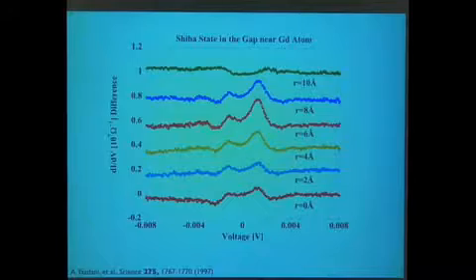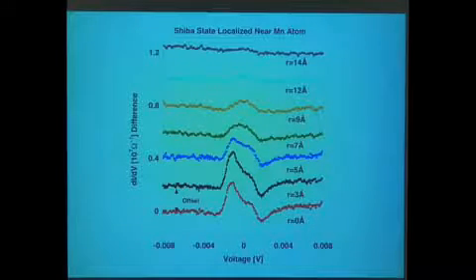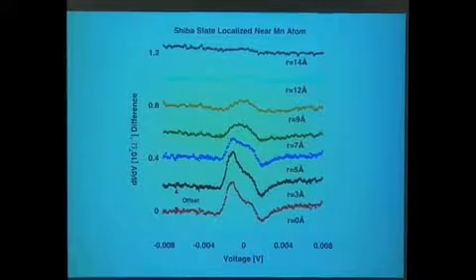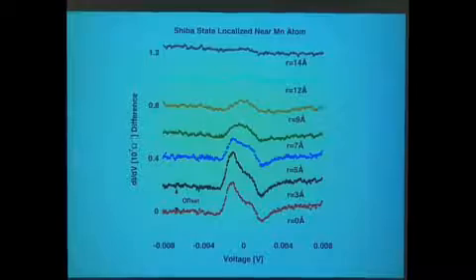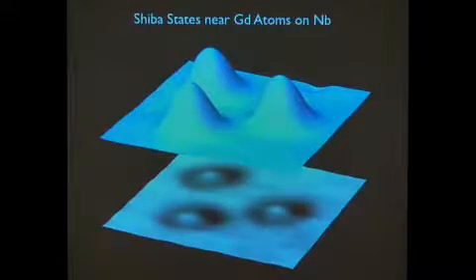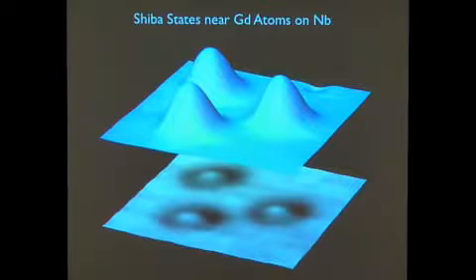And it depends what atom you put there. If you put manganese, you get states at a different energy. The details don't matter. We actually understand this in great detail, these data having to do with just the exchange interaction of a spin impurity with a superconductor. Ferromagnetic or antiferromagnetic? These are single spins. It will happen in either case, yes. But do you know the sign? No, we know the size because we can match the state's energy. What's important is that we can map them in real space, and this is where they live. They live around these impurities. They're very short range.